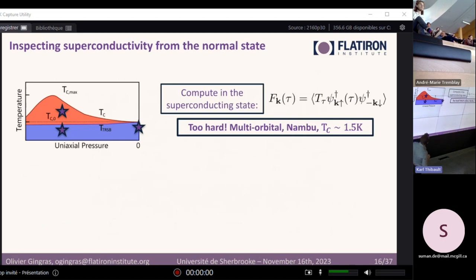So the question is, how do you study superconductivity numerically? What kind of numerical simulation will give you this information? What we would like to do is perform a computation, for example, in the superconducting state at zero strain. Then we could extract the whole Gorkov function, which tells us about the pairing of the electrons. We can look at what irreducible representation this satisfies, and then we would have our answer. We could do the same calculation at these two stars here. You could look at what the irreducible representation is here, and what it is here. That would be very nice, but it's really too hard to do numerically, as I pointed out before, because it's a multi-orbital system. In the Nambu basis, we need to expand the basis. And most importantly, the critical temperature is so low that we never reach that.